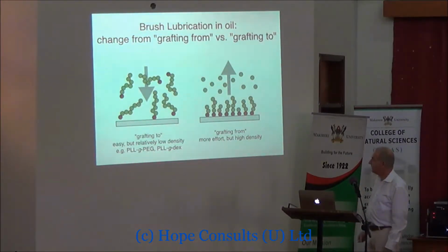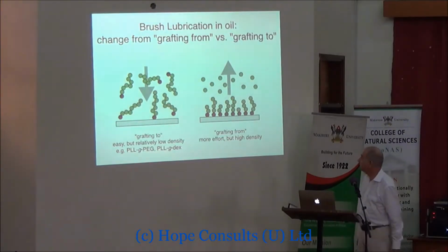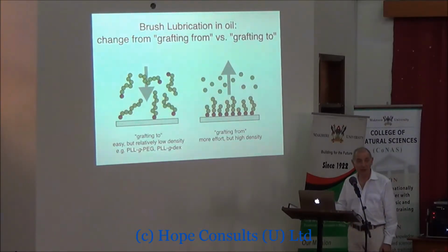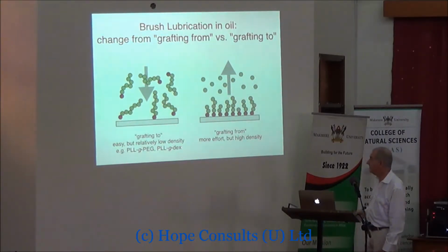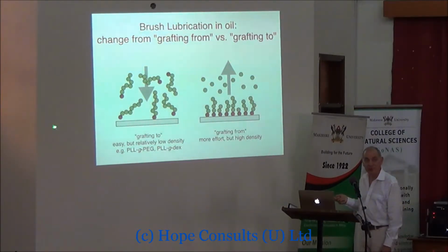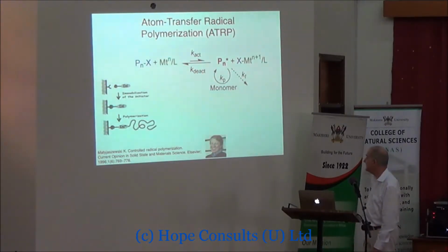After doing a lot with lubrication in water, we started looking at lubricating in oil. Obviously, oil lubrication is more relevant, especially when it comes to the automobile industry. And this was no longer really a possibility. We couldn't use charge to attach our polymers to the surfaces anymore. So we decided to use this grafting from route, where we put initiators on the surface and then we grew polymer chains out of the surface. And we used a technique called atom transfer radical polymerization, invented by Chris Matyjaszewski in the United States.